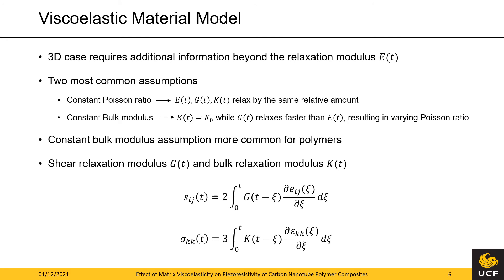In the three-dimensional general case, additional information beyond the relaxation modulus is required to describe the mechanical behavior fully. In the elastic case, the Poisson's ratio is often chosen as the additional parameter and assumed to be constant. However, this is overly simplified in the viscoelastic domain and leads to the same relative relaxation of the bulk relaxation modulus and the shear relaxation modulus. Another common option for viscoelastic polymers is the assumption of a constant bulk modulus, which is often closer to reality since the relaxation under hydrostatic pressure is very small. These assumptions are necessary since often not enough data is available to determine bulk and shear relaxation modulus independently.